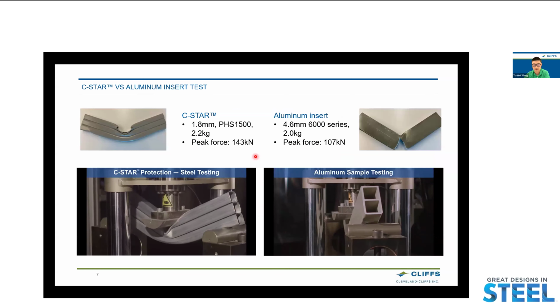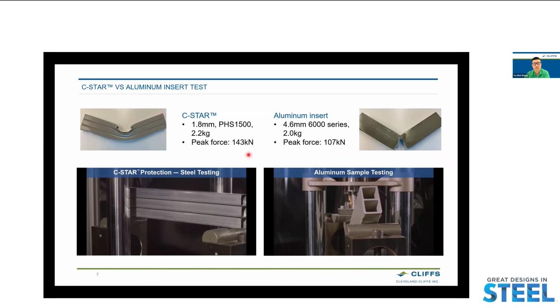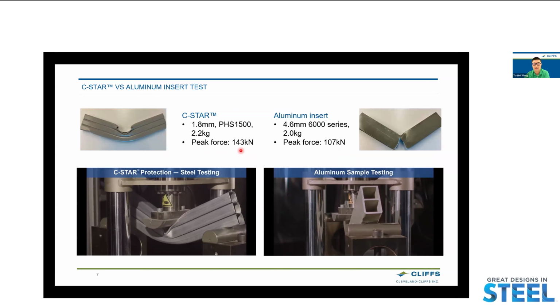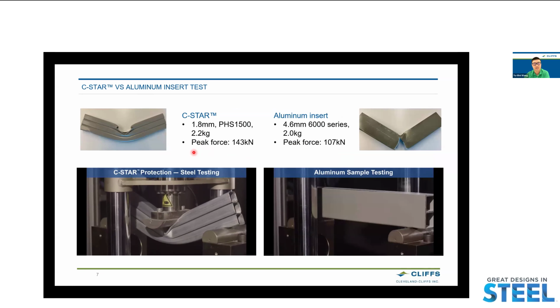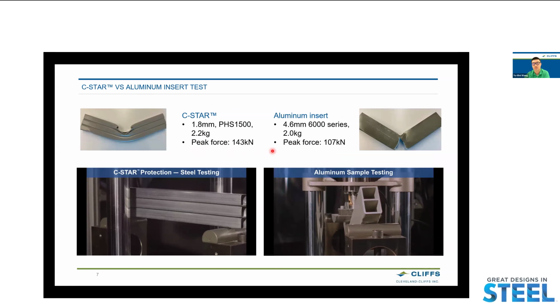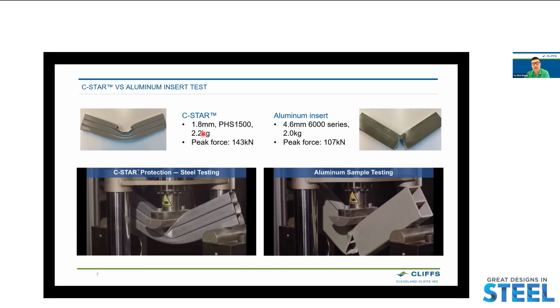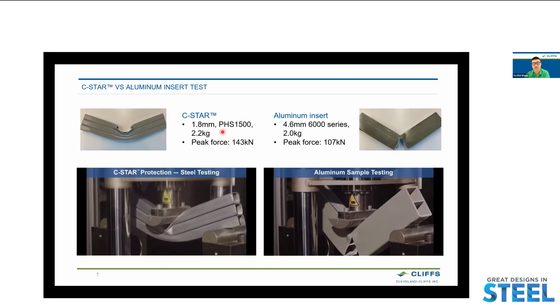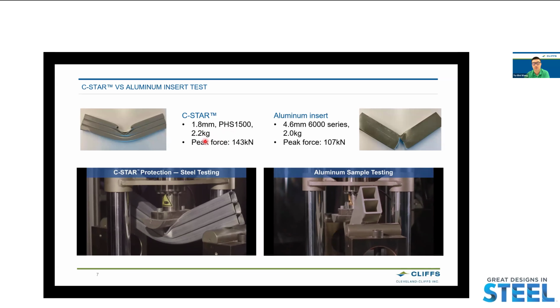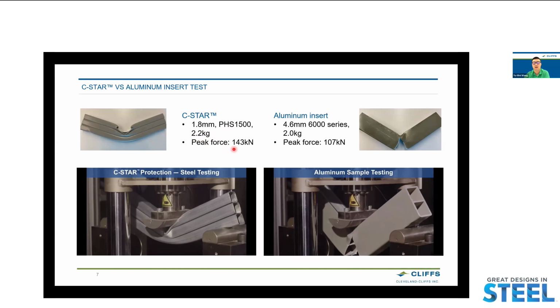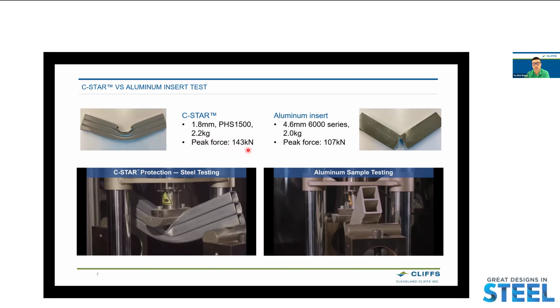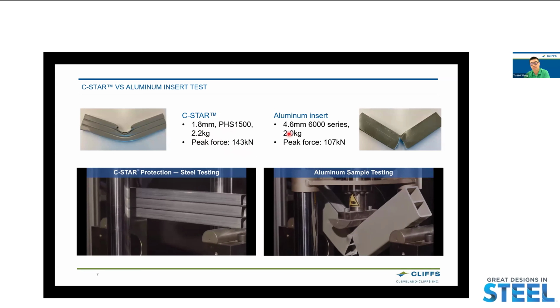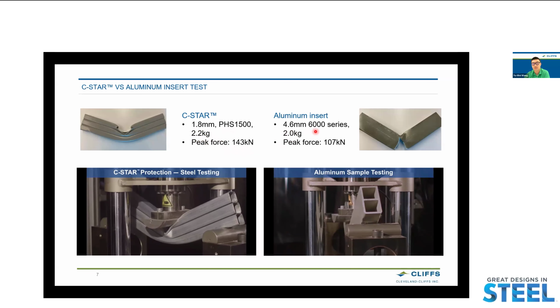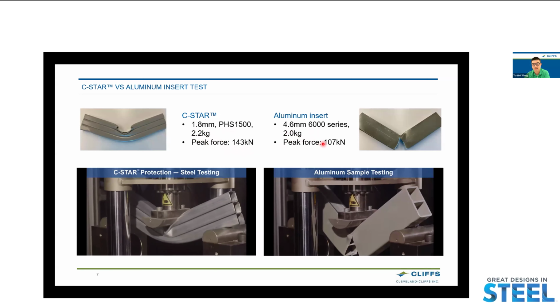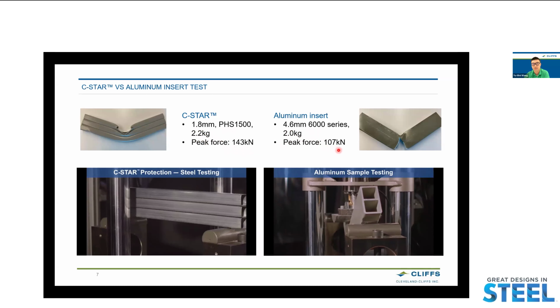Now let's take a look at the test results. This is a comparison of our C-STAR and aluminum test. The left-hand side shows the C-STAR results. The right-hand side shows the aluminum test. For C-STAR, as I said, we are 1.8 millimeter with PHS 1500. It weighs 2.2 kg. The peak force is 143 kilonewton. For the aluminum, it's 4.6 millimeter, 6000 series. It weighs 2.0 kg. The peak force is 107 kilonewton.